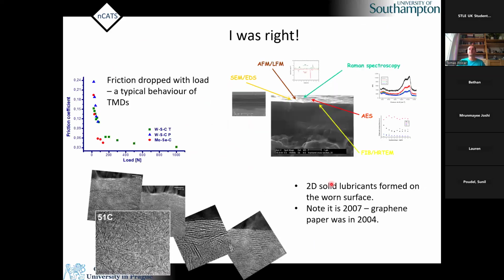But what is important is to be bold but supportive. So what I did at that time was demonstrate that, for example, friction dropped with load, which is typical of these solid lubricants, nothing to do with carbon. Then I really did a lot of tests on the tribolayer. This is the worn surface, and I investigated it by scanning electron microscopy and EDS, which everyone is doing now, but it was not that common at that time. I used atomic force microscopy to measure nanoscale friction on the surface to show that there is very low friction typical of these solid lubricants. I used Raman spectroscopy, which was almost not used at that time for tribology, and a lot of other stuff, including high resolution transmission electron microscopy. Note that it was in 2006, 2007.